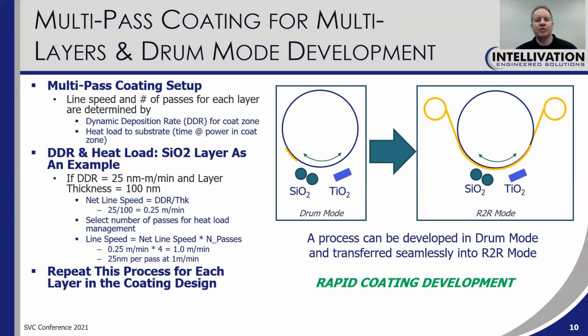So what do I mean when I talk about multi-pass coating? In this case, we're going to take 1 layer in the coating design and distribute that across multiple passes just to manage the heat load. The way we determine these settings is, first we characterize the dynamic deposition rate in the tool, and then we go through and determine an acceptable heat load for our particular substrate. By way of example, if we have a DDR of 25 nanometers per minute and a layer thickness of 100 nanometers, we calculate the net line speed being 25 divided by 100, or 0.25 meter per minute.